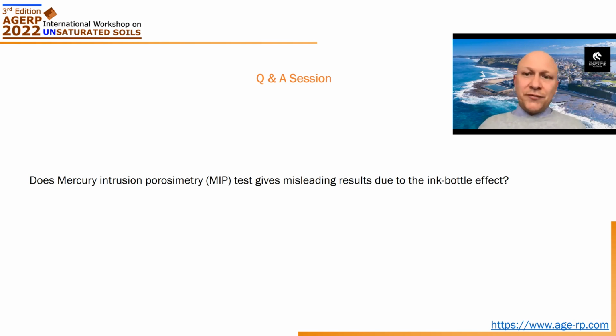Now, we've recently conducted, with that image I showed you at the end, some image analysis on the mercury intruding the specimen to try to characterize the ink bottle effect, and it's not necessarily very pronounced. So if you take it as relative information about relative change of microstructure, maybe there are not so many changes in the ink bottle effect, and the relative information is something you can trust.